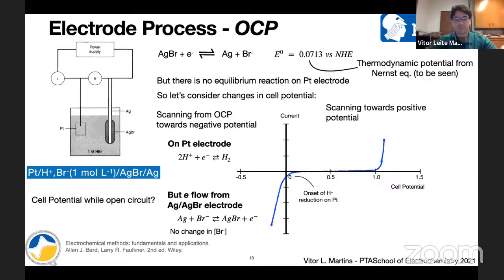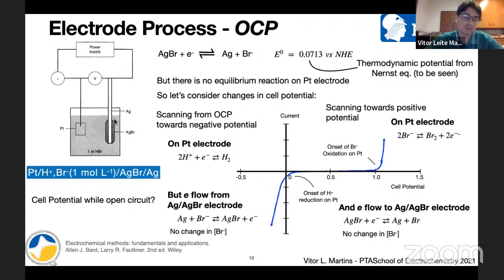So in this example, we have two electrodes, right? One electrode has a reversible equilibrium reaction occurring here. So these two reactions, you understand that we have two reactions, right? One goes to the right and one goes to the left. The potential at which these reactions occur at the same rate is known, right? So this is the potential. And platinum in this solution doesn't have any reaction occurring in equilibrium. So there is no oxidation of platinum and reduction of platinum at the same rate occurring in this system, right? So what's the potential of this electrode? We don't know. It's not possible to measure this potential.